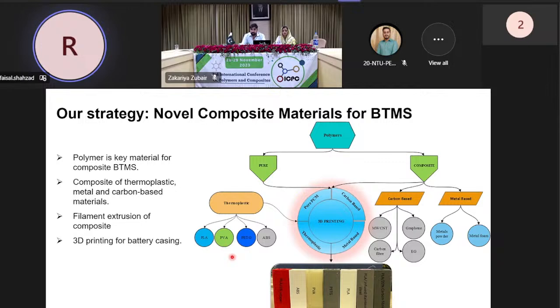So for composite filament extrusion, we mixed thermoplastic with different carbon-based and metal-based materials, then made a filament and printed with it. You can see we printed different battery casings with ABS, PVA and PETG, and we also mixed 80 to 20% stainless steel powder into those filaments.